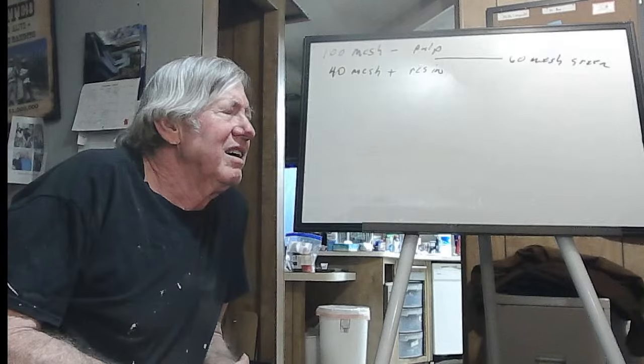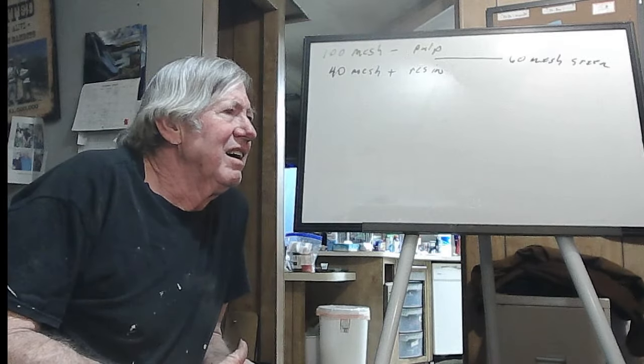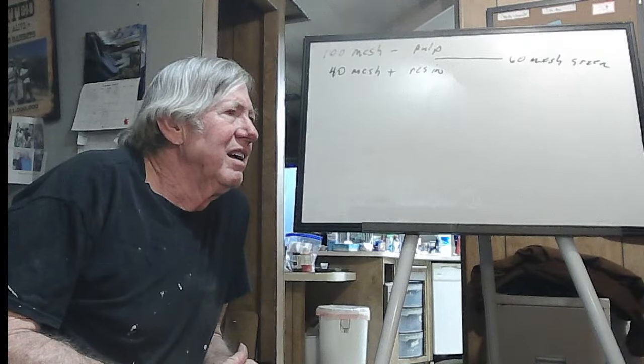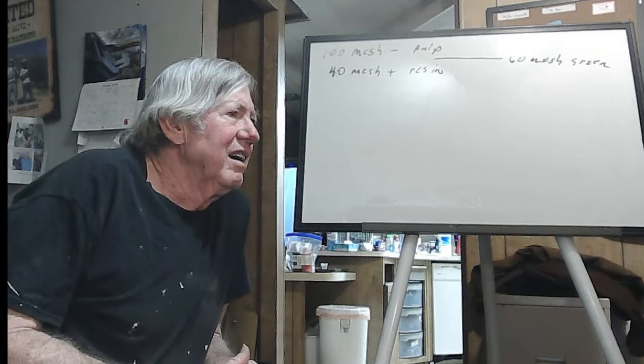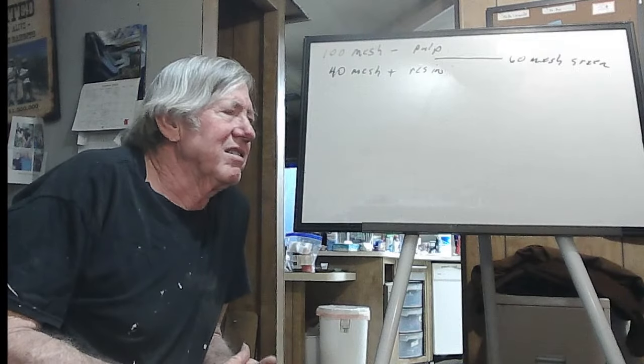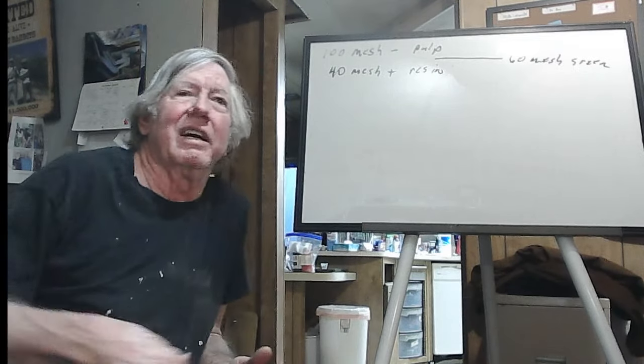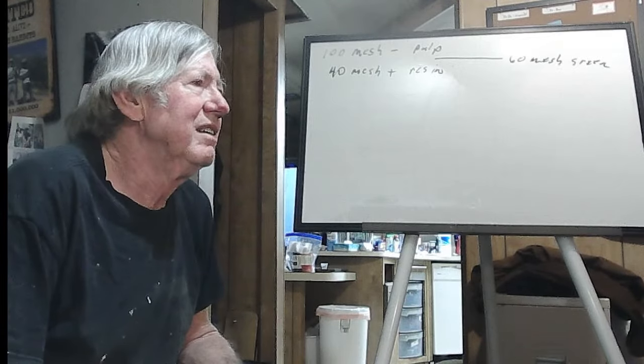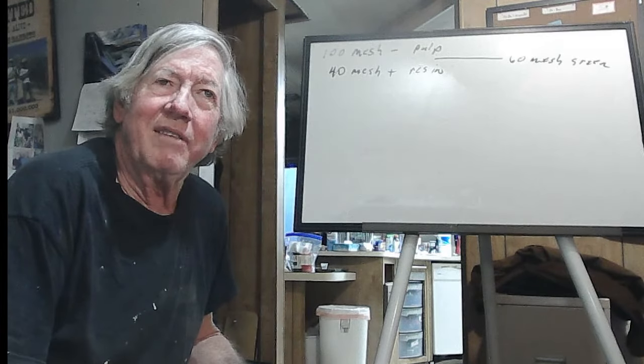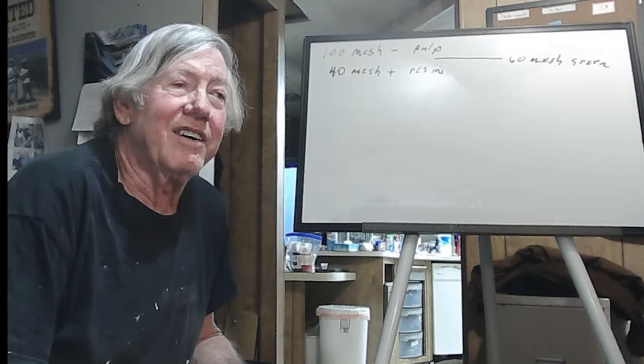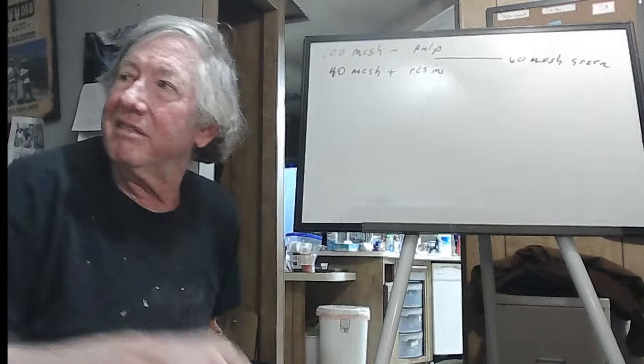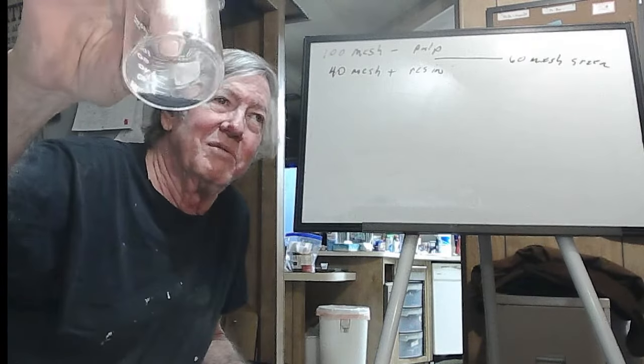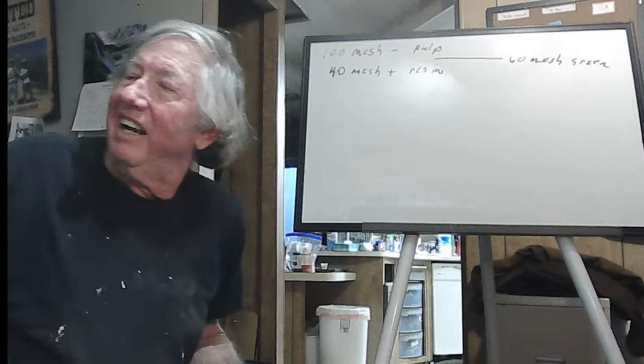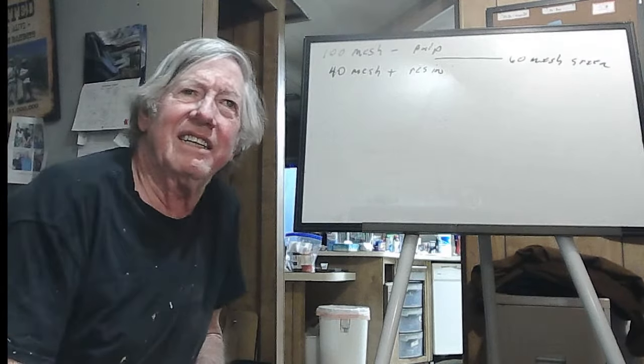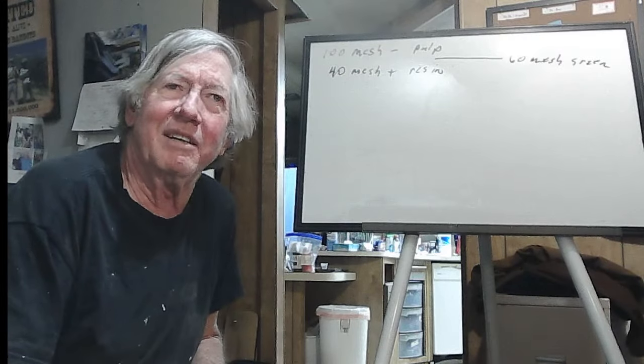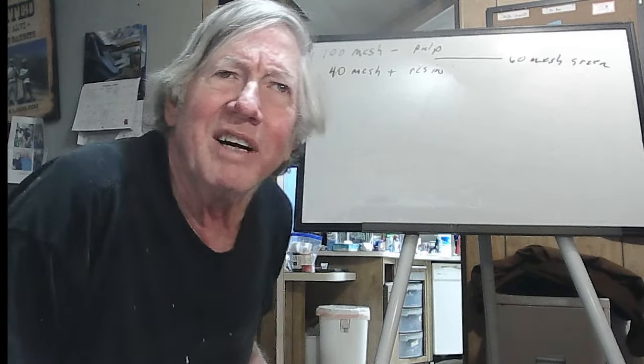I know we thought we had significant residual. Did we smelt some of the old stuff and get any numbers? I smelted the old stuff, and I got numbers that showed there was very minuscule gold left, less than one. So we got it pretty clean of gold. According to Eva's memory, when we fire assayed the resin, and that's why we have some dry loaded resin here, it indicated we had gotten well over 95% recovery from the resin.